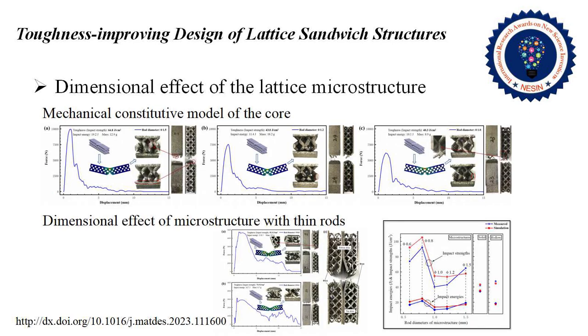And the experiment results show that, for the BCC lattice sample with thick rods, in the process of fracture, tear-type cracks appeared in the core. The absorption effect of the energy of tear-type cracks is higher than that of open-type cracks. In addition, the lattice structure can ensure enough materials in the direction perpendicular to the crack surface. The plastic zone can extend along the rods of the microstructure. The core rod diameter is relatively thick, such that the impact load can be easily transmitted to the bottom by inclined rods. Then, the crack is caused at the V-notch.